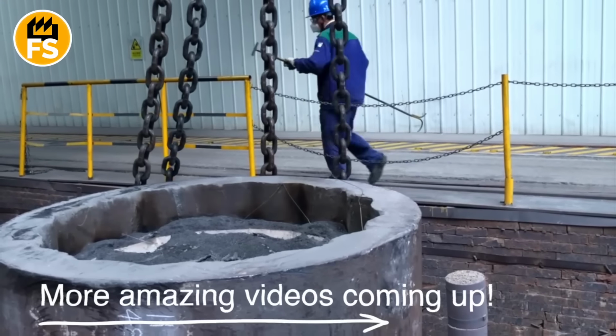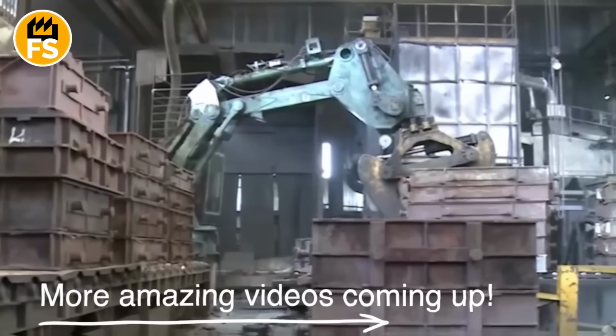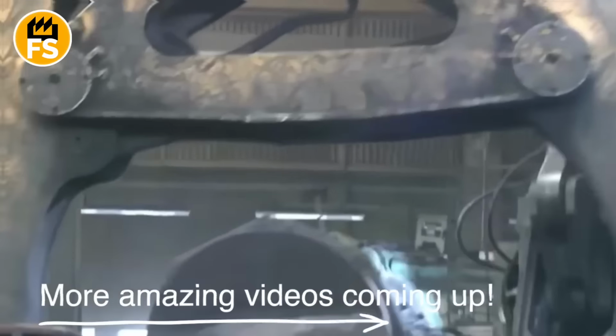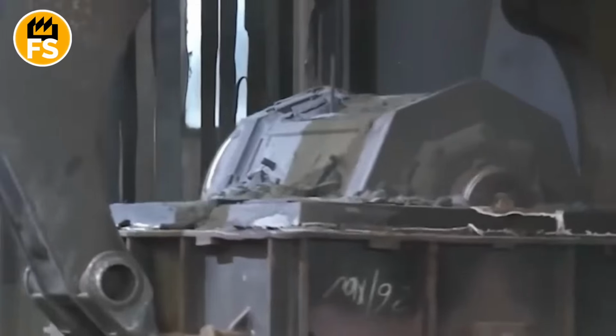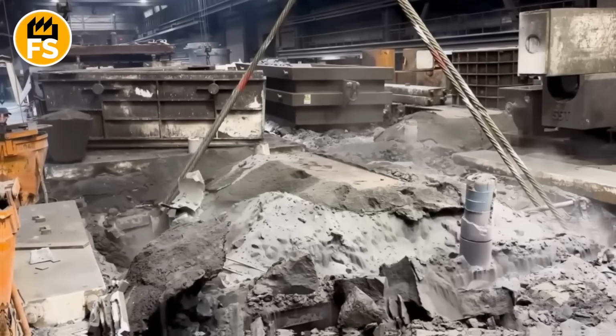To ensure uniformity of the crystalline structure, the 607-ton ingot was left to cool in the casting pit for 6 weeks. This is a controlled, incredibly slow process, during which the steel gradually solidifies, dropping to a temperature of around 2,000 degrees.